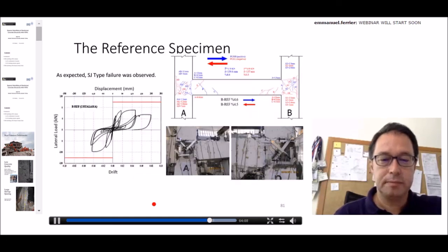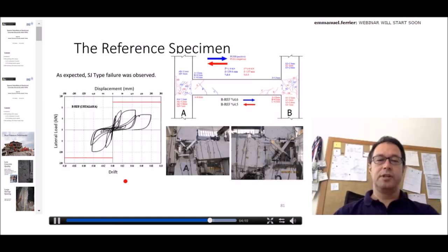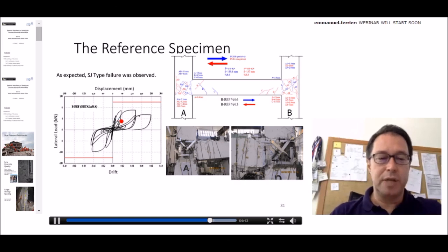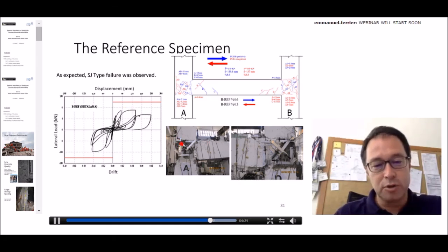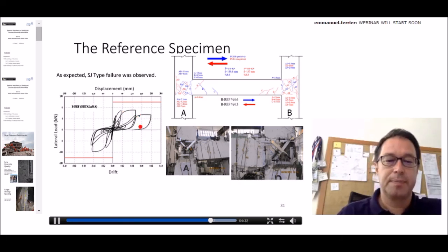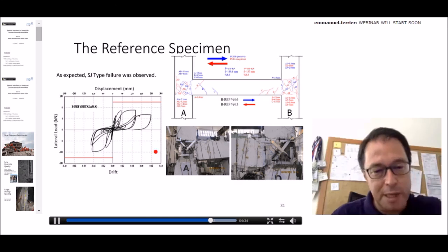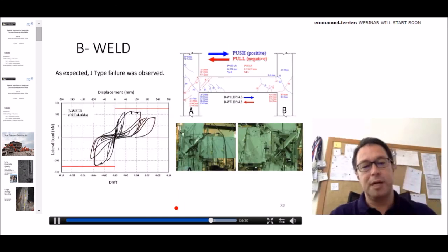And this is the behavior of the reference specimen. As I said, very similar to the sub-assemblage tests. We had much lower strength than theoretically expected because of slip of beam longitudinal bars and the damage due to concrete crushing in front of the hooks of longitudinal bars. And then we had joint damage, joint failures somewhere here, which is not a very bad behavior, but the strength is much lower than we could expect.